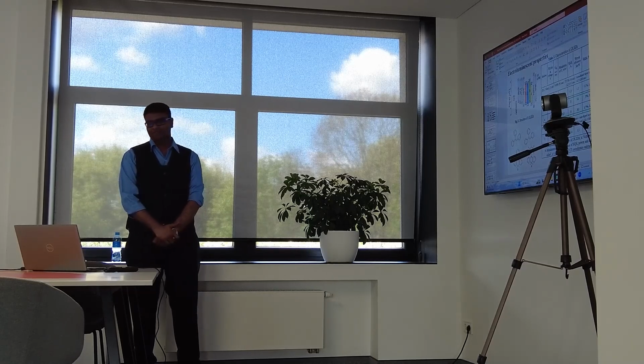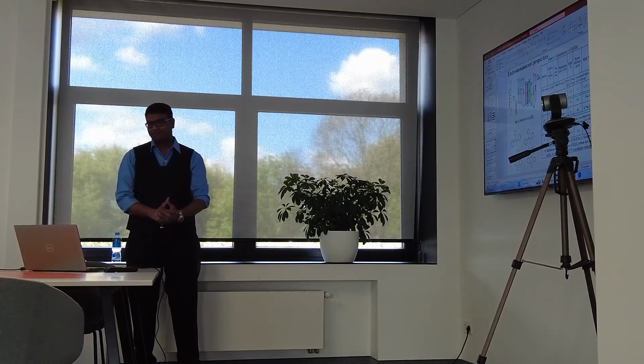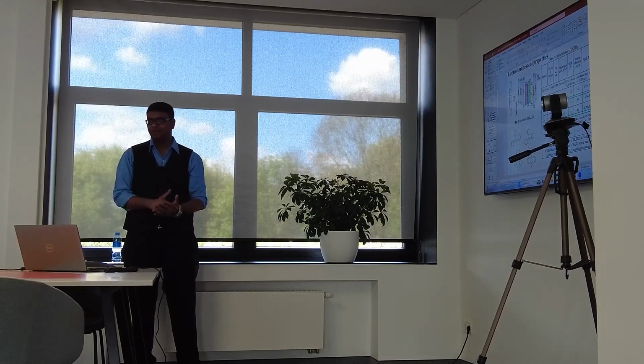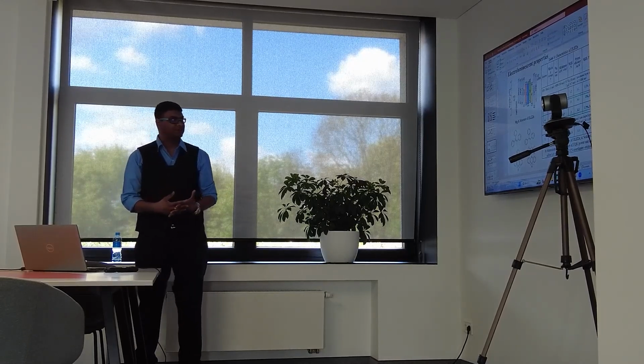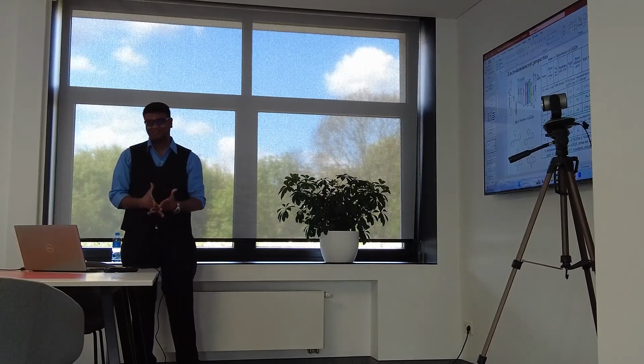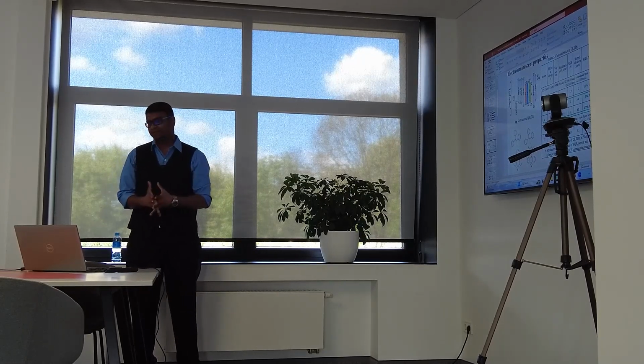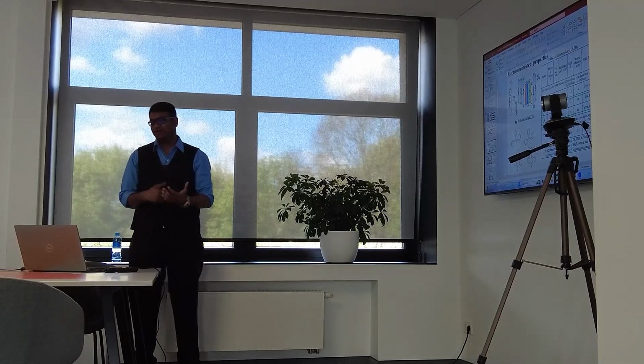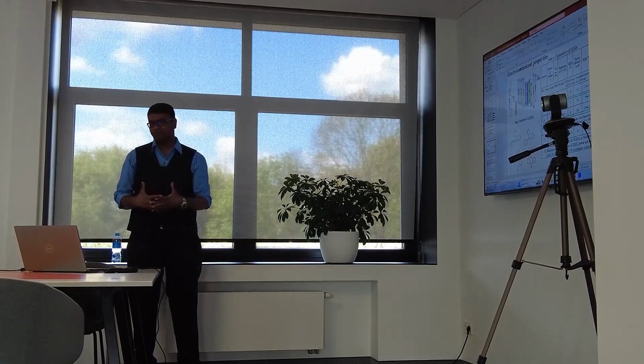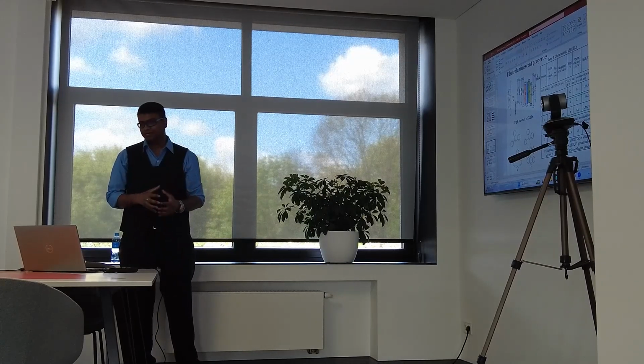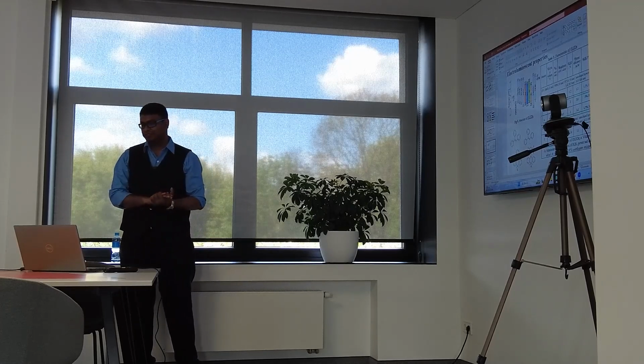Okay, well, in this case these are fluorescent type devices, and usually the EQEs for fluorescent type devices are limited to 5%, and at this point we can say that the efficiency of 2% was more or less reasonable. The possibility to increase efficiency is to try to use these materials as thermally activated delayed fluorescent type materials, because the compounds with fluorine atoms showed such possibility. So in that case we can try to increase the efficiency of the devices.